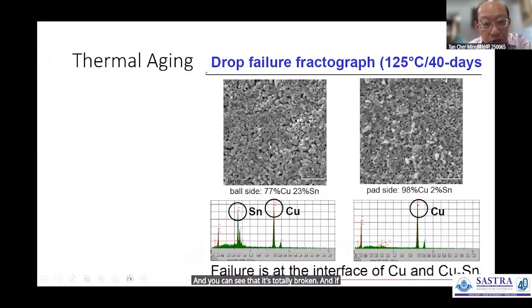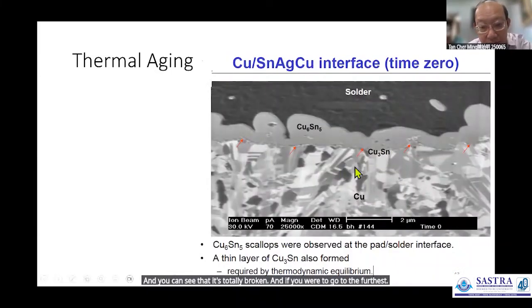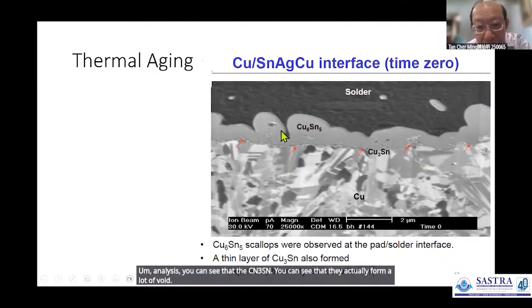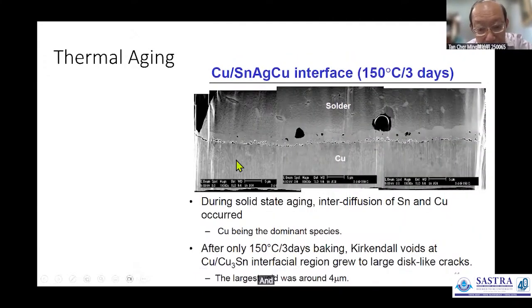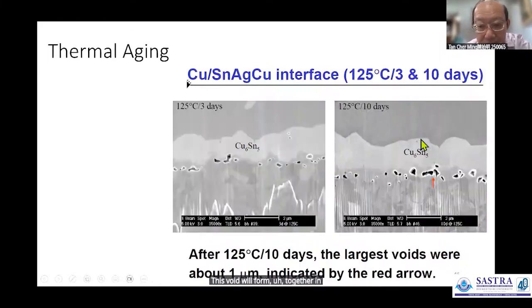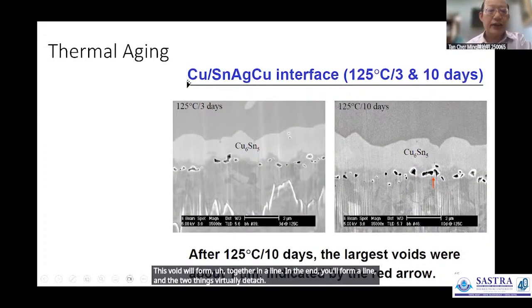And if you were to go to the further analysis, you can see that the Cu3Sn, they actually form a lot of voids. And these voids, as you go over time, for 150 degrees C, 3 days, will form together in a line. In the end, it will form a line, and the two things virtually detach electrically.